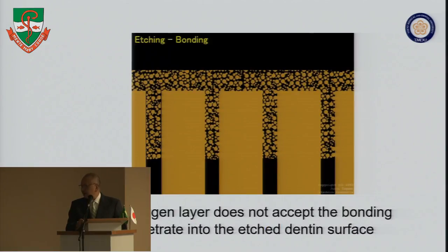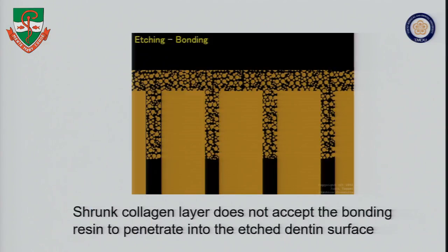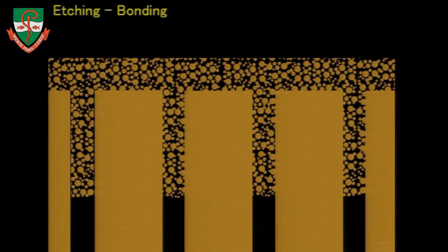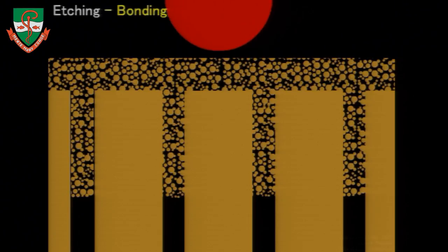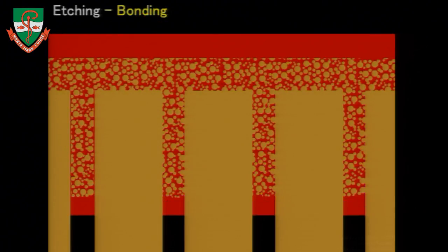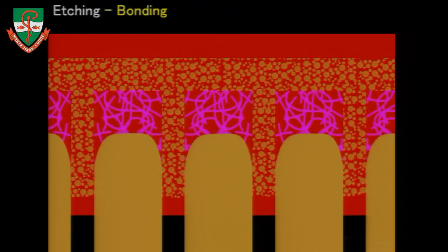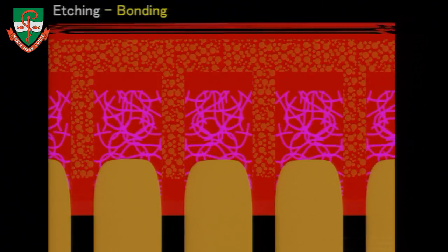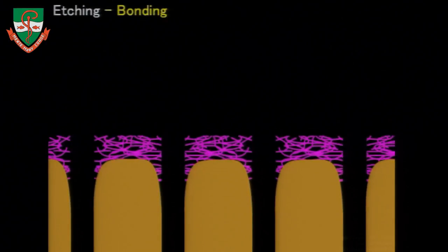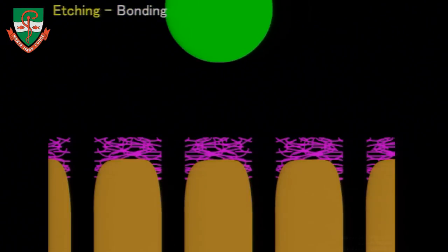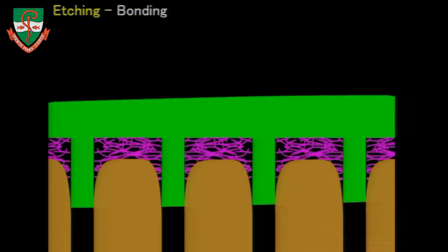Now I'll show you a very simplified animation of the bonding mechanism in the case of the etch and rinse technique. This is a dentin surface covered with a smear layer after the preparation. The phosphoric acid is very strong. In a very short time, the smear layer is removed and the surface of dentin is demineralized. The collagen layer is exposed here, and after rinse and drying, the collagen layer shrinks. Because of the shrinkage, the space in the layer becomes so small. That's why the bonding resin cannot penetrate into this layer so well.